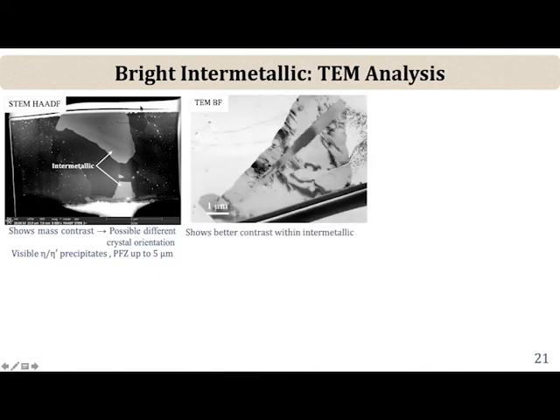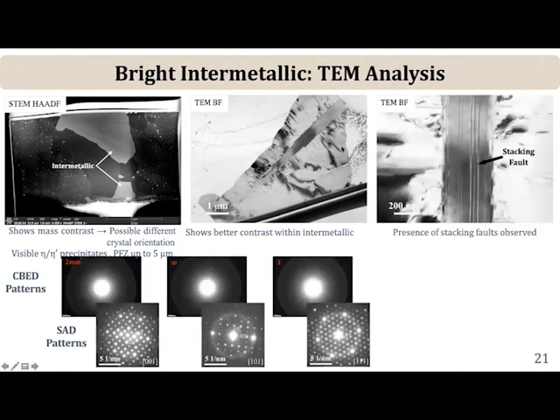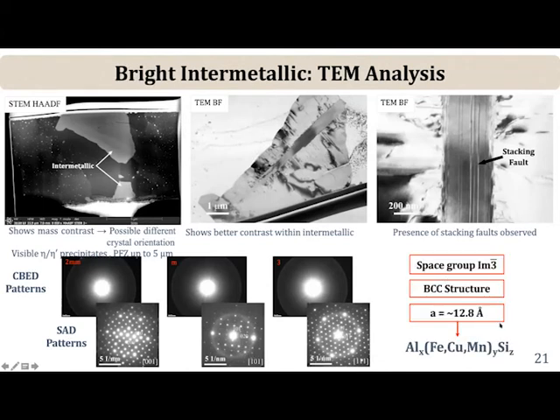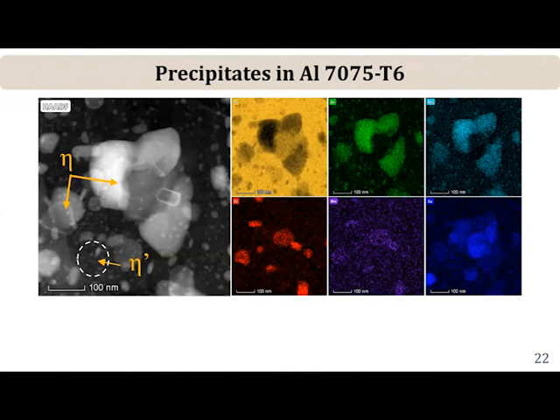This shows a FIB foil. You can see the bright MgZn2 or eta prime precipitates. And this is an area where there's been some depletion. And some of these coarser intermetallics, as I mentioned, are actually aluminum iron silicon compound, which is a well-known compound. It has a BCC structure with a big lattice parameter. Now, one of the things is that the microstructure of 7075 is fairly complex. As I mentioned, these are STEM EDS maps showing various kinds of precipitates. The fine precipitates are eta prime. Some of these coarser precipitates are eta. Some others are rich in copper and chromium. Some of these coarser precipitates are actually different kinds of compounds, but the fine ones here are MgZn2.